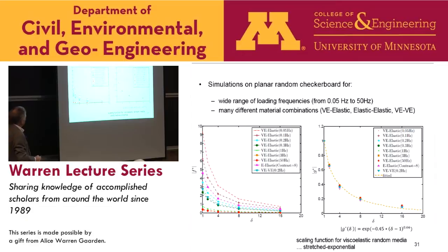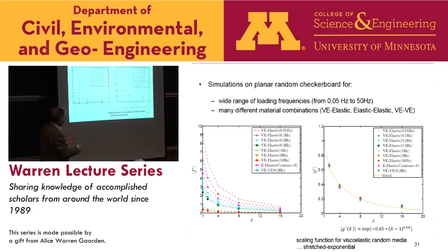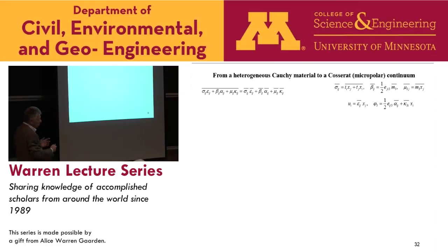And we actually went for the scaling function because the whole problem kind of should be analogous to linear elasticity, from linear viscoelasticity. And lo and behold, we got the same form, stretched exponential, of the scaling function here again. For various kinds of combinations, various kinds of material systems. All of them, in the end, can be mapped onto one functional form. One can also play this game for